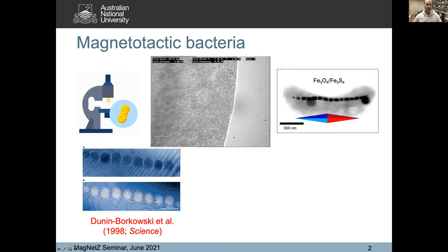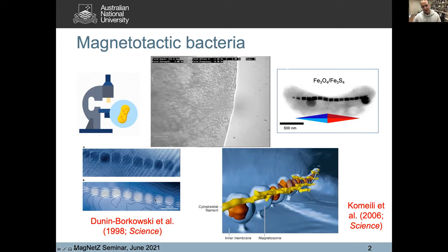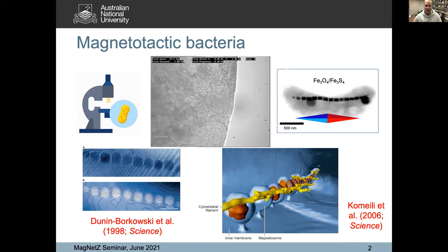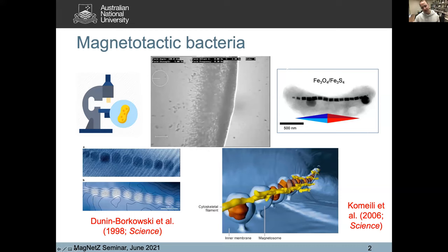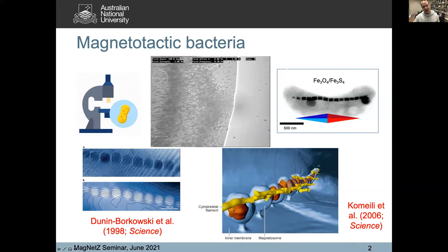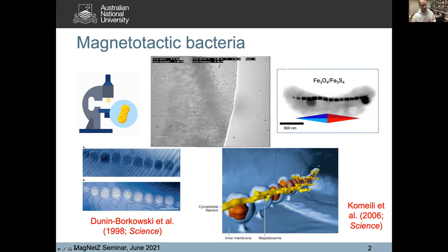If you look at a TEM image of those magnetic particles in a magnetosome chain, they're not independent — they're strongly interacting, but interact such that they're flux-linked. You see a large single dipole associated with that single magnetite chain. This is from electron holography. The magnetosome is the organelle within the cell, and magnetite or greigite is biomineralized perfectly within it. The chain structure is held together by cytoskeletal protein filaments which line everything up — it's an extremely intricate and beautiful structure.